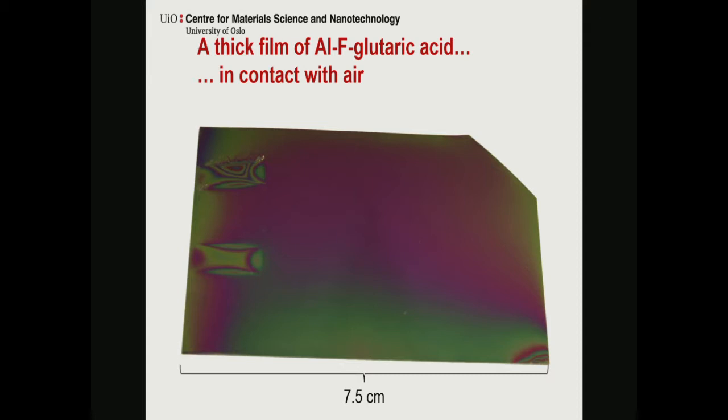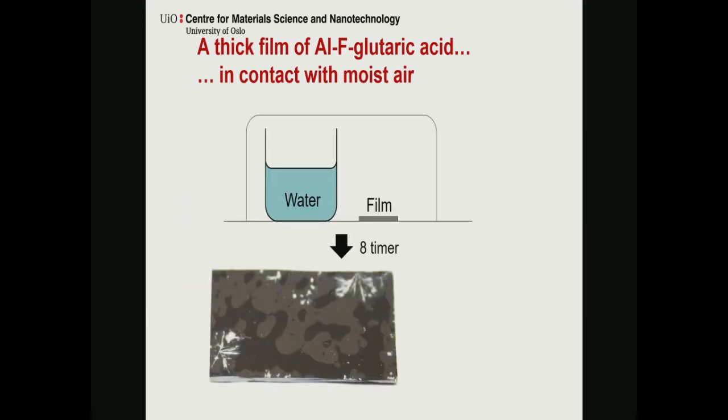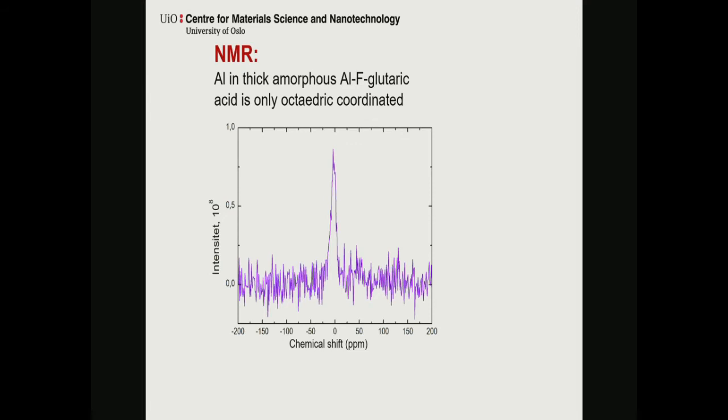This film here, we expose to air. And this film here is, yes, it's true, 1.7 micrometers. This grows nicely. So for going into this MLD type of fashion, we are going to be able to discuss with the PVD people again. But within 30 minutes, it increased by 200 nanometers. And when you expose it to higher saturations of water, you do get blisters, you do get some additional features. But then, what about aluminium?